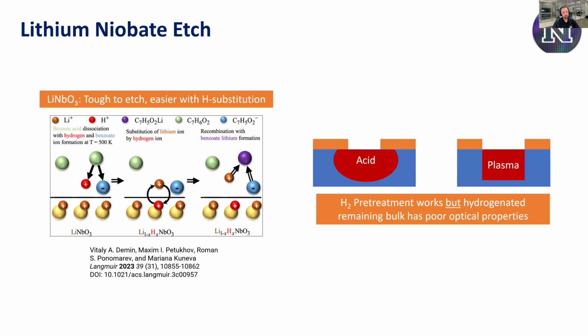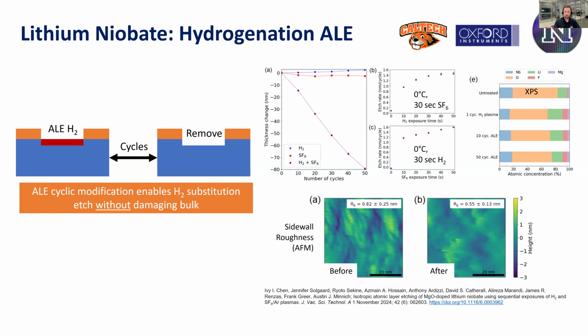And they were able to as well show reduced sidewall roughness, and the XPS shows they weren't getting undue contamination of the material or anything. Of course, hydrogen doesn't really show up in XPS, but they did some work on that as well. So there's all these other approaches to ALE as well.